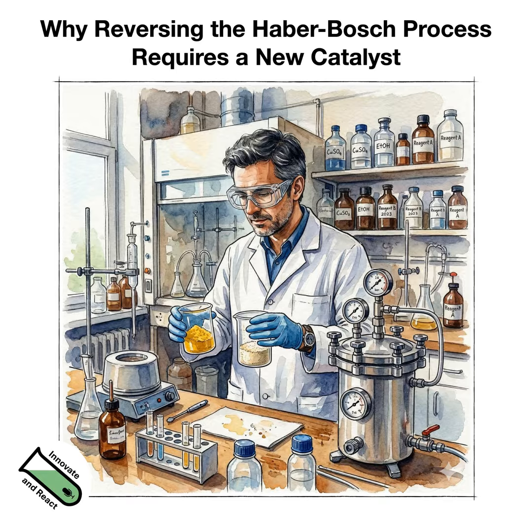But then you don't want them to grow larger. You don't want them to form extended structures, because all that would mean that there would be ruthenium atoms that are unused in the bulk of those larger particles. And for iron, we simply don't care too much. And we can make the pore walls, we can create them from the iron particles because it is affordable.